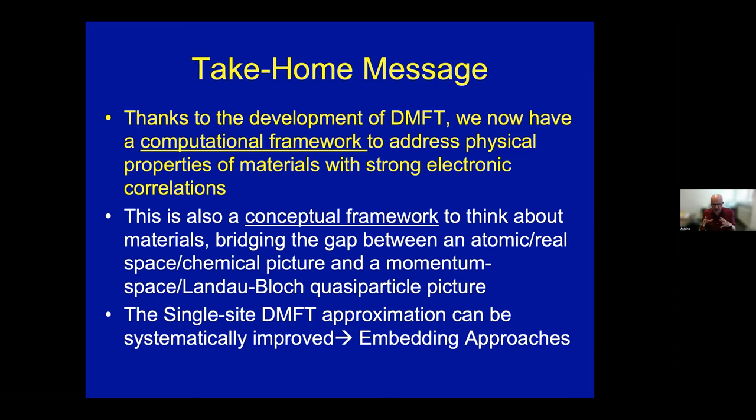So if you actually perform a single-site DMFT calculation for the 2D Hubbard model, let's say, let alone cuprates, in this regime, you're going to find that everything is very uniform around the Fermi surface because things are not momentum dependent. But in reality, we know that the low-doping state of cuprates has reasonably well-defined quasiparticles near the diagonal directions, the so-called nodes, and very incoherent, basically no quasiparticles in the horizontal and vertical directions, the so-called antinodes. And in these directions, there's a pseudogap that forms.